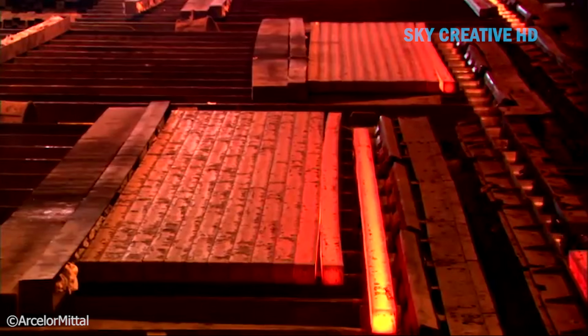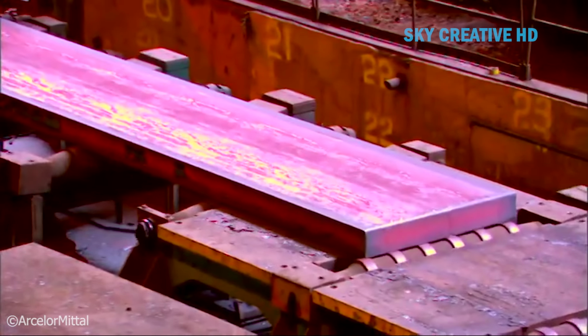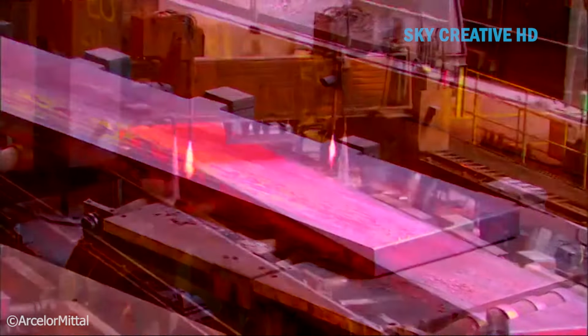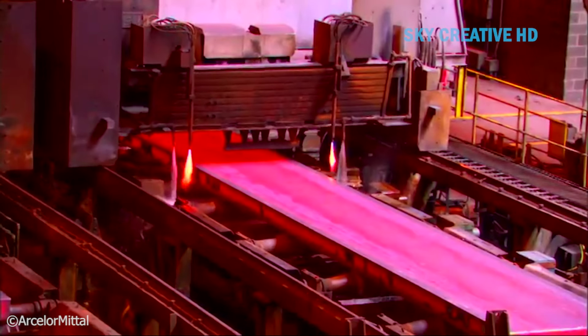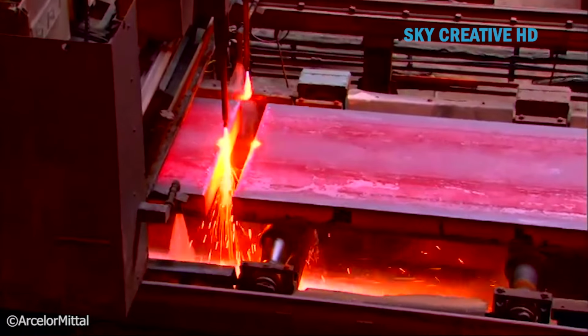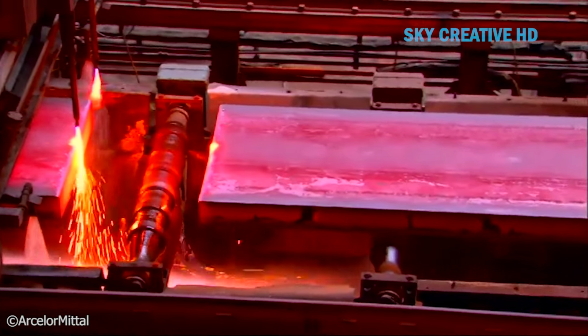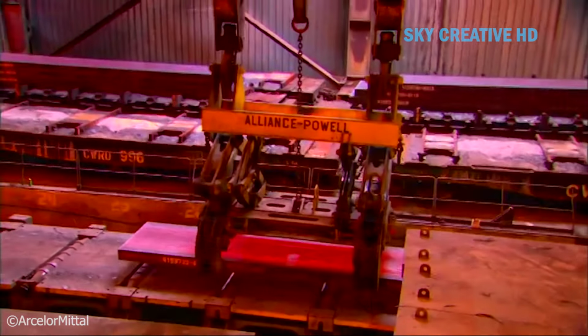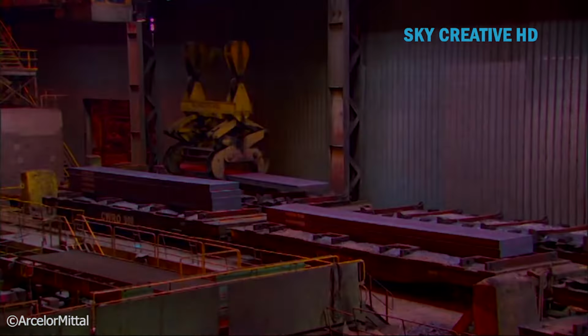The final stage involves the hot strip mill, where those massive slabs are transformed into coils. The roughing mill reduces thickness through a series of powerful rolling stands, each applying thousands of tons of pressure. Then the finishing mill, with its 7 stands of 4 high rolling mills, brings the steel down to its final thickness, sometimes as thin as a few millimeters.